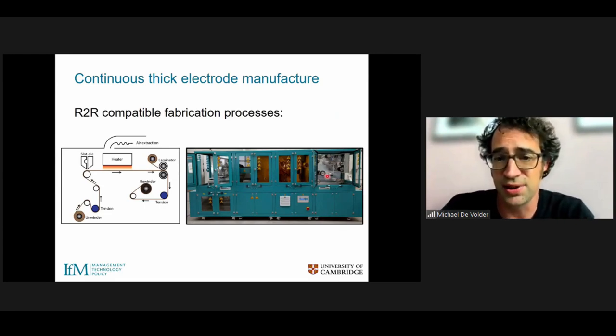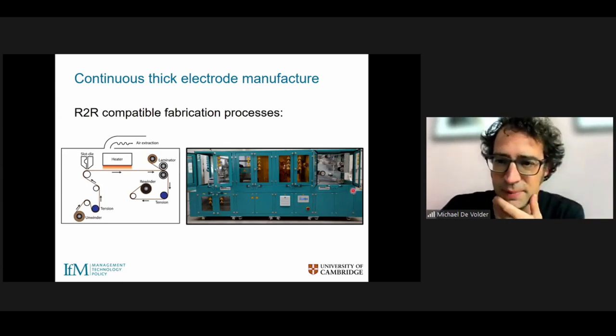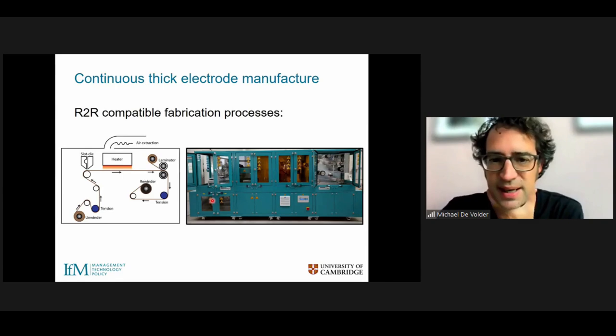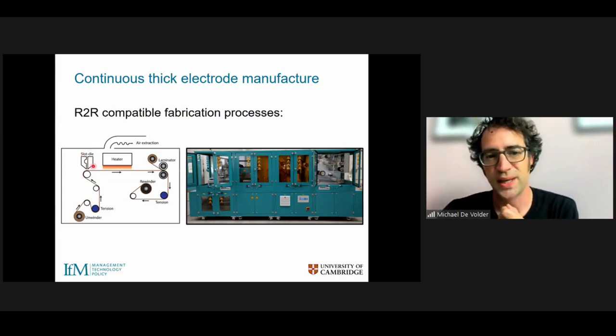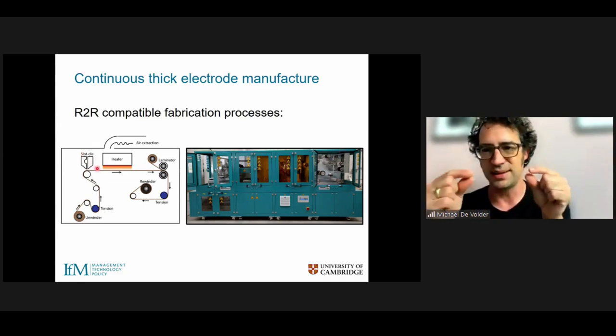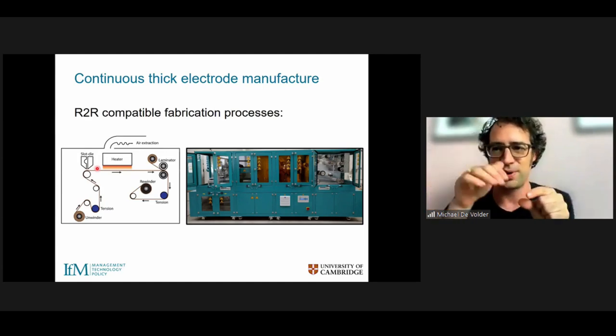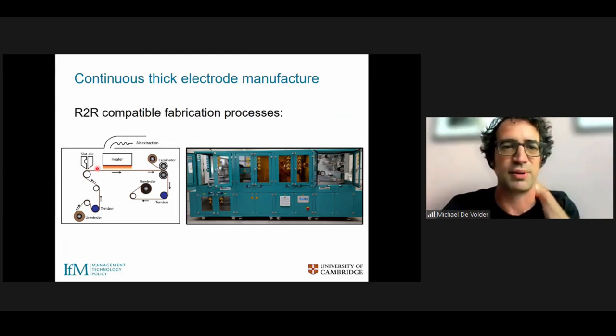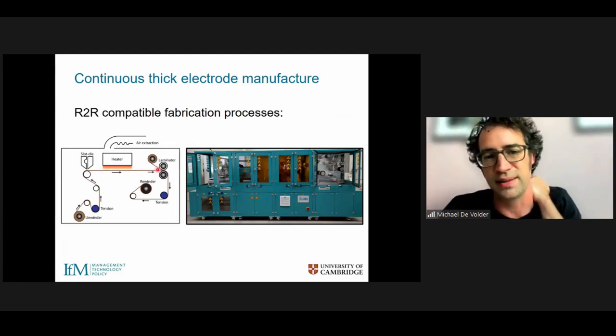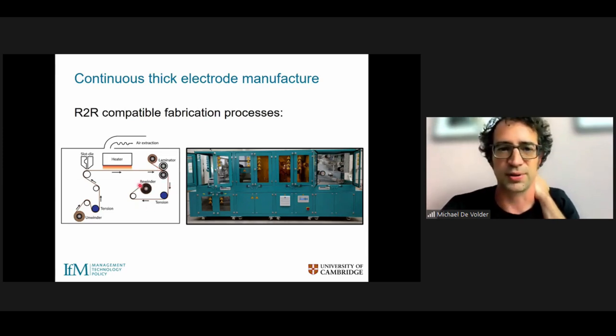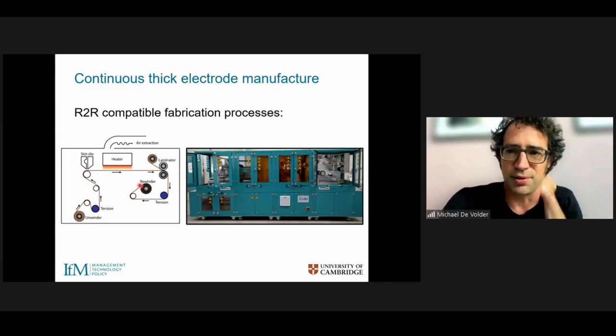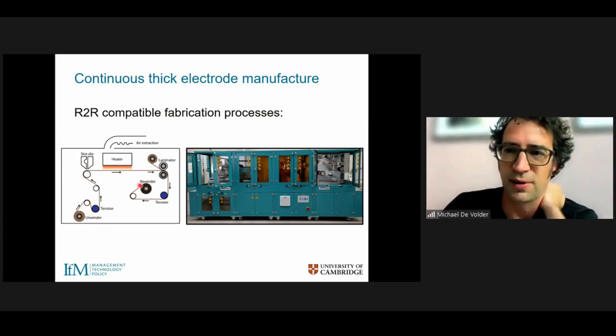And so the process used by industry is called roll-to-roll coating. And so you can see an example of such a tool from my lab here on the right-hand side. And although it looks complicated, it's fairly simple. So what we have to do inside is just take a stock roll of metal foil, we tension it, and then we do a process called slot die coating, which is nothing more than just having a little slit in a coating head through which we squirt some slurry containing the active battery materials, which is then dried as I just explained. Optionally, you can laminate it with the protective foil and then rewind your coated battery material. And that's all there is to it, but doing this with thick electrodes turns out to be complex.